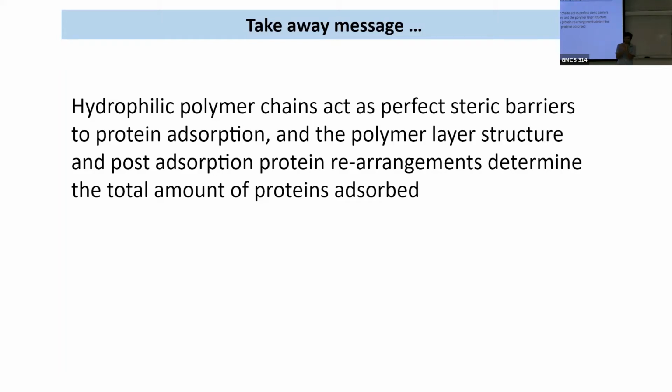It's like, look, I have this polymer which has all these water molecules surrounding it. There's the energetics of the protein interaction, there's the energetics within the chain for its gyration, and there's a lot of things determined by the energetics in the medium. Sure, right? So we don't need that for this. Yes, there are energetics involved. My point is that for the protein to pass through this polymeric barrier, if the barrier height is say 30 kT, that height is so much that it's not going to jump over within the time frame. It's very unlikely for it to jump over this high energy barrier.